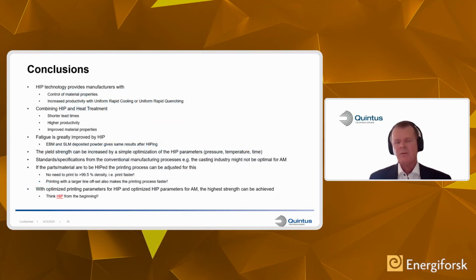So basically, to finish off, the HIP technology will provide improved mechanical properties, and not only that, you can control the process, and you can also achieve productivity gains using the press as a heat treatment furnace, which will give you shorter lead times and improved material properties. Fatigue, as I mentioned, is greatly improved with the HIP process, and also the yield strength, by having the possibility to optimize or vary the HIP parameters, which are the pressure, time, and temperature. You can improve your mechanical properties.